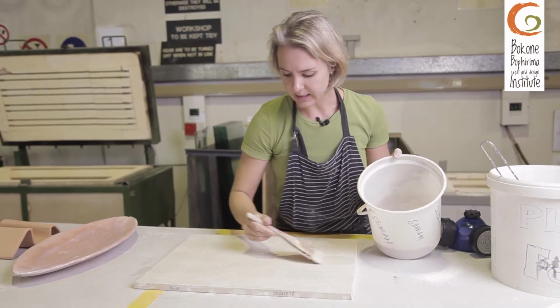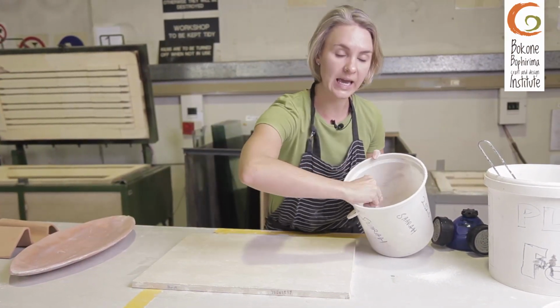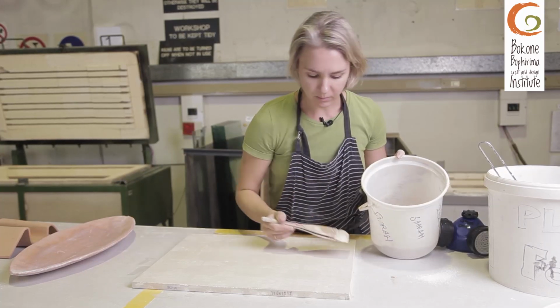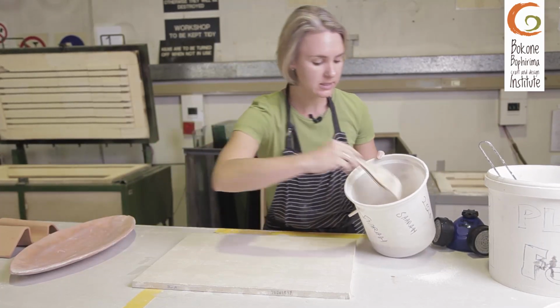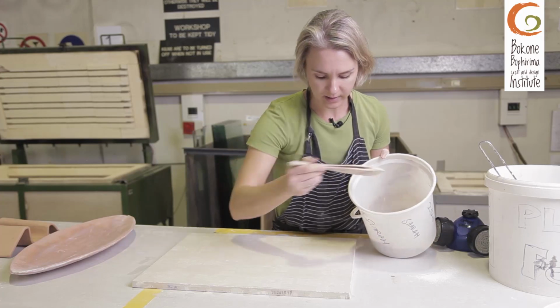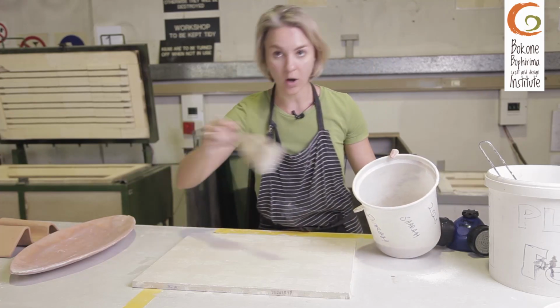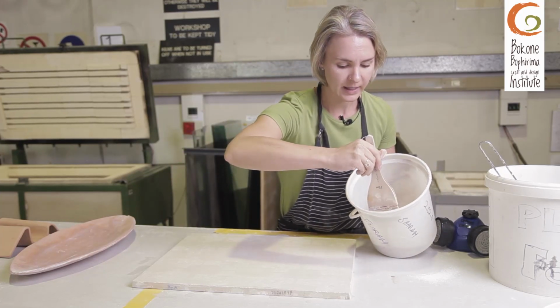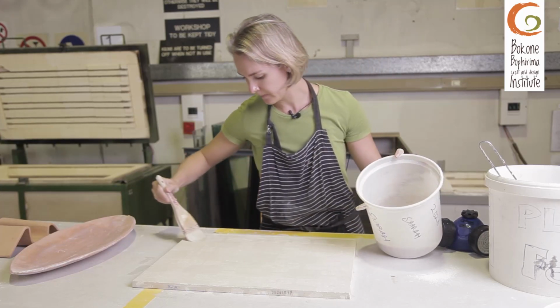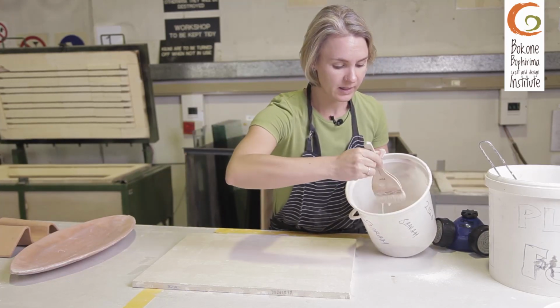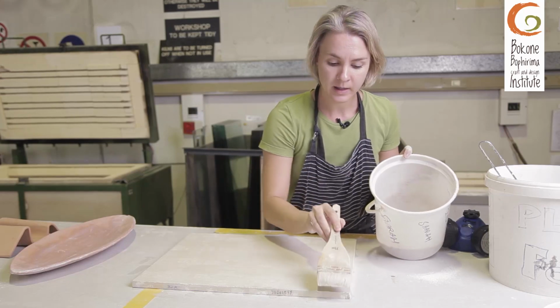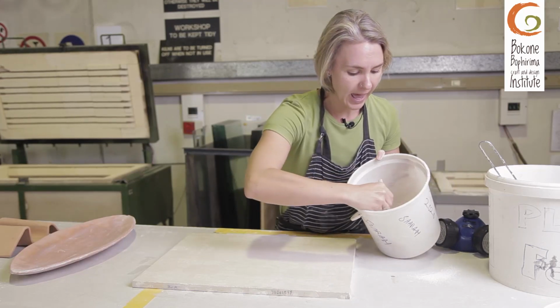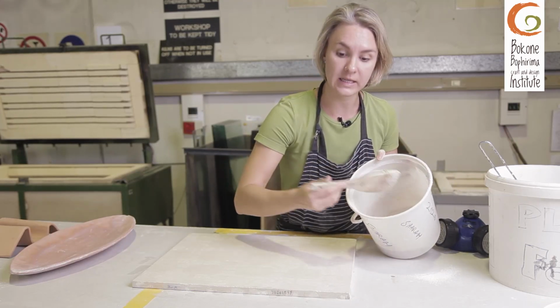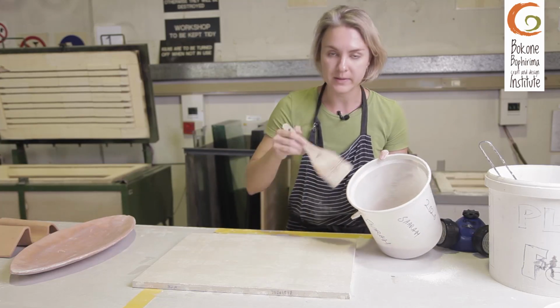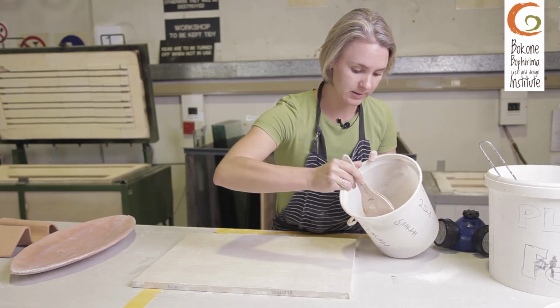And it's a good idea to do this the day before, because you want the kiln shelf to be completely dry before putting your glass on top of this kiln shelf. If there's still moisture on your kiln shelf, it will create steam, and that can also cause devitrification or bubbles on the surface of your glass.